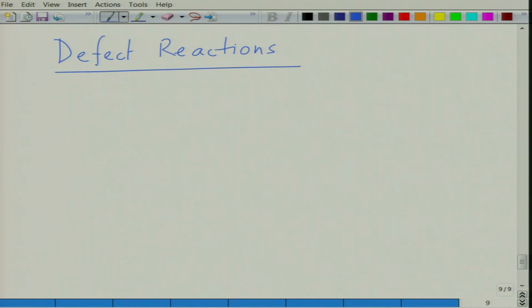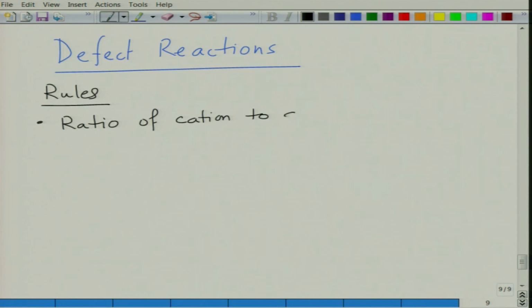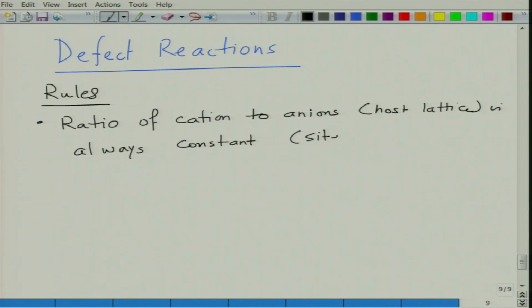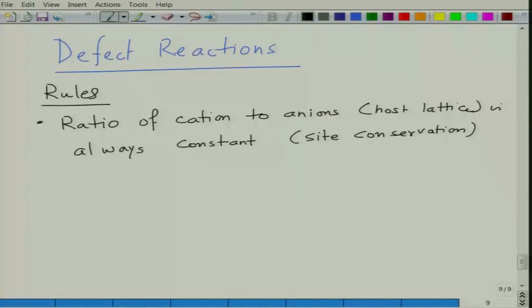So we need to follow certain rules. The first one is that the ratio of cation to anion sites for the host lattice is always constant. It's a law of site conservation. If it is an AO lattice, which means the number of A sites is equal to the number of O sites, you cannot change that ratio. You cannot make it A2O3 or A2O. AO is the host lattice.